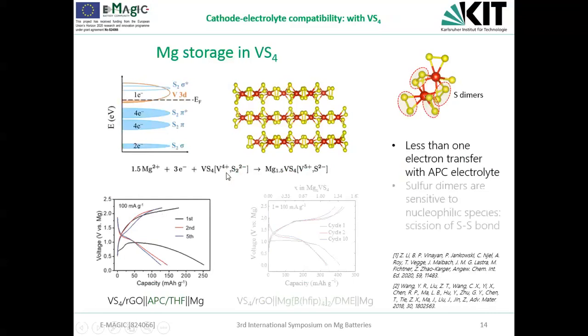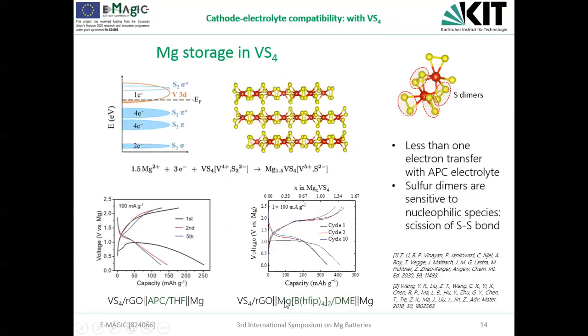But if we switched to this borate electrolyte, we have much improved capacity, and also we have a very nice plateau. A possible reason could be that the sulfur dimer we have in this VS4 structure is quite sensitive to nucleophilic species. So if it's coupled with the APC electrolyte, then we have the breaking of the sulfur-sulfur bond, so of course we have a relatively lower capacity.